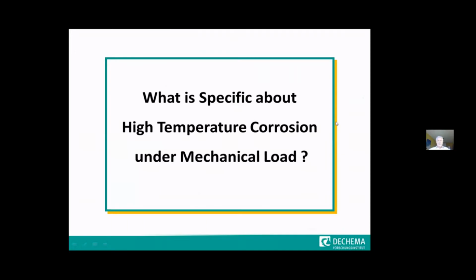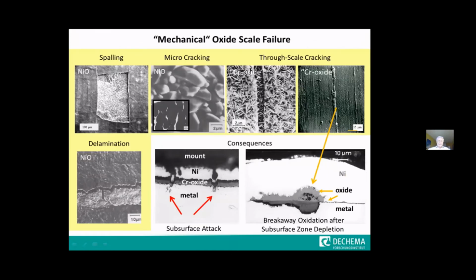So I think, first of all, we need to talk about what is specific about this interaction between high temperature corrosion and mechanical loads at the same time, affecting the life of these materials. Now, I don't know how deep you are in high temperature corrosion, but usually, pretty much the same as in electrolytic corrosion, these materials survive as soon as they form a protective layer, a passive layer, on the surface.